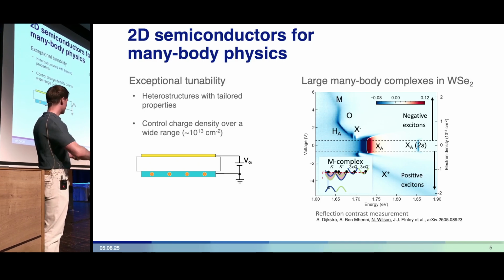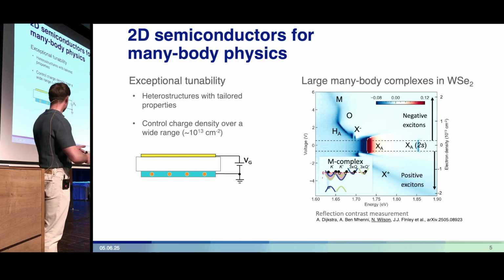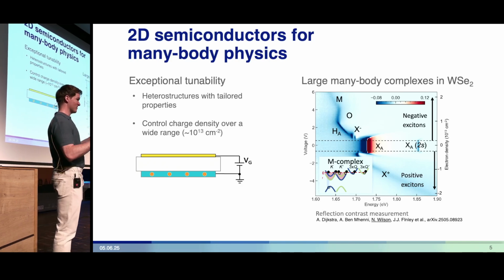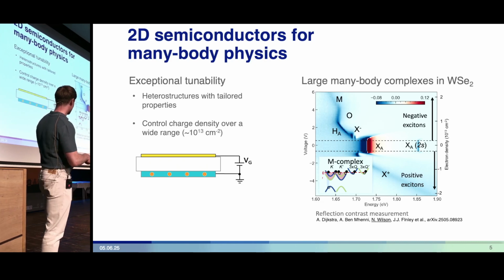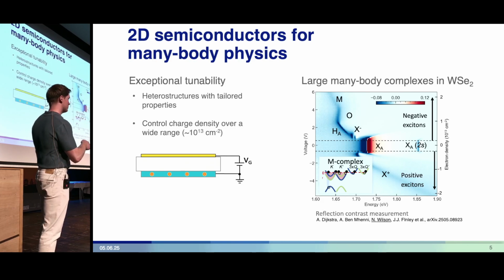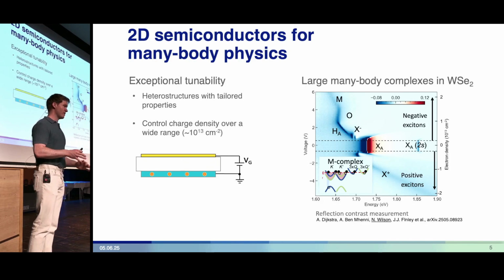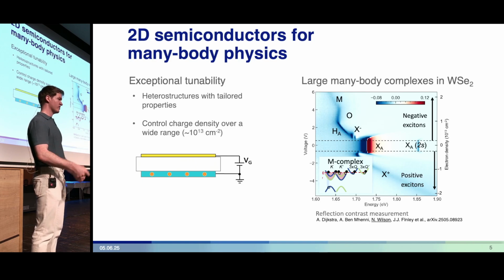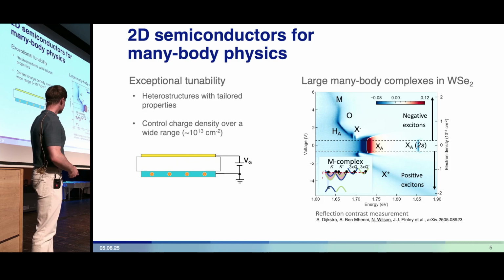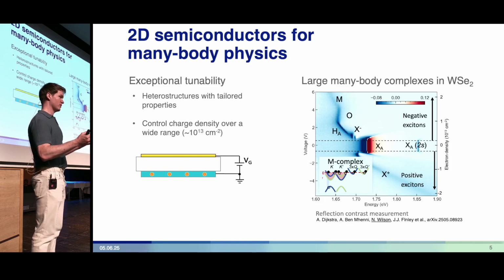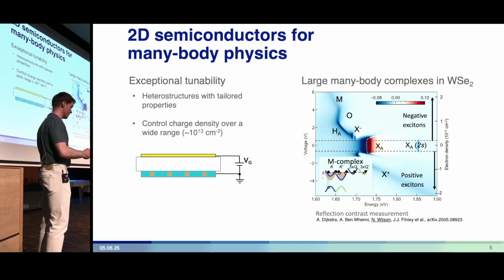And so, putting together strong interactions, excitons, and controllable charge density, it turns out that we can already see some first effects of many-body interactions in the exciton spectrum. This is recent work from my group and the group of John Finley, where we show that we can form many-body excitonic states consisting of up to 20 excitations living across 10 different Fermi seas, all bound together into a single quasi-particle. This is a very interesting thing that can happen. You form these big states, and it really shows you how strong interactions in 2D semiconductors can be.